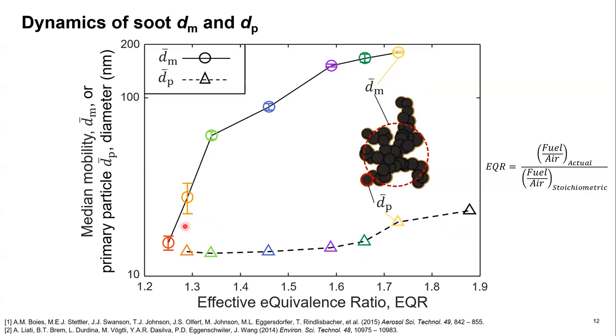Focusing on the leaner equivalence ratios, which are more aircraft-like, we see that our 14 nanometer primary particle soot is right in the middle of the range typically observed in aircrafts, which ranges from 10 to 20 nanometers for the median.